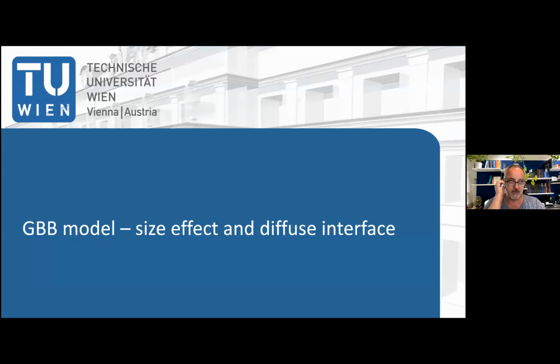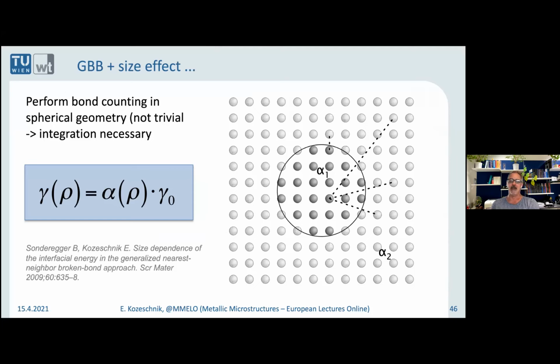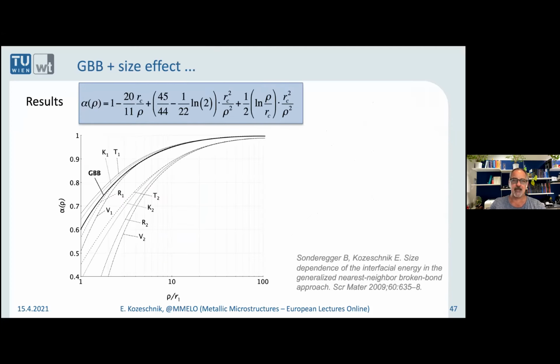Yeah, the next thing that we observed was once the nucleus becomes rather small, then our predictions are also not so good as we wanted them to be. And what we realized quickly was that if you have a curved surface, like a small precipitate with a highly curved surface, then the number of bonds that go across the boundary are much less compared to the planar interface. And we worked on that and came up with an analytical expression for the effect of size on the interface energy. So I'm not going into too much detail. It's an analytical expression. So it's this factor alpha as a function of the radius, and that's normalized with respect to the nearest neighbor distance.